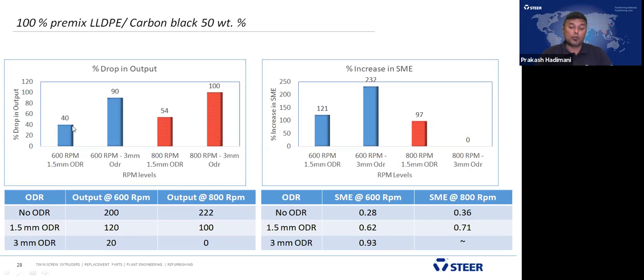And 40% output drop at 600 RPM with 1.5 millimeter OD reduction. 90% output drop at 600 RPM with the 3 millimeter OD reduction. At 800 RPM with 1.5 millimeter OD reduction, 54% drop in the output, and 100% drop at 800 RPM with a 3 millimeter OD reduction, meaning 1.5 millimeter per side. It's a 100% drop in the output, meaning nothing, it's zero. And if you calculate the SME power consumption, at 600 RPM, 1.5 millimeter OD reduction, the SME increases 121%, and at 600 RPM 3 millimeter OD reduction, 232% increase. And in the case of 800 RPM, 1.5 millimeter OD reduction, 97% increase in the SME.